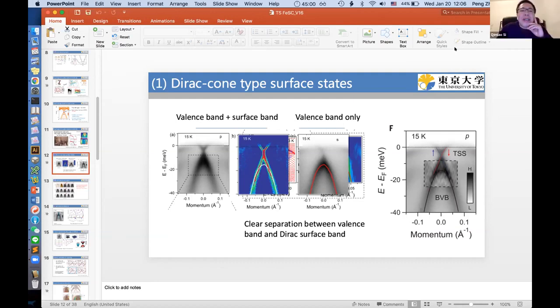Maybe I can even follow up on that. So the band inversion is supposed to be between the D and the P state. So is the PZ state ever seen? Also, I can mention that in lithium iron arsenic, the band inversion is very clear. We observed that. But for this 1-1 system, the PZ band did not show a clear dispersion along KZ. Okay, but where is the PZ band in this? For lithium iron arsenic, I can show. Yeah, only for lithium iron arsenic; for the 1-1 system it is not that clear.